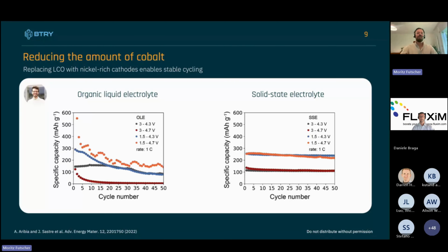So to start off with the cathode work, this is really work which was done by Abi Abdesselam, who is also one of the co-founders of BTRY. And he showed that he could fabricate a new material with these vacuum coating processes in a thin film format. And then he also showed the difference between using it in an organic liquid electrolyte, like the classical lithium-ion batteries used today, or in a solid-state electrolyte. So if you go to a liquid electrolyte, you typically cycle somewhere between 3 and 4.3 volts.